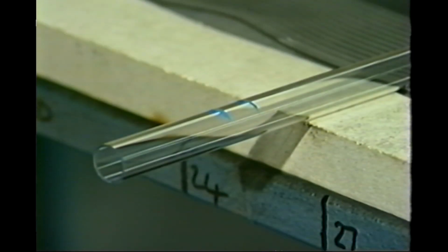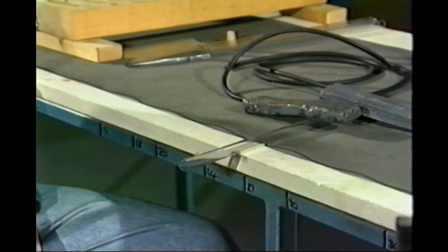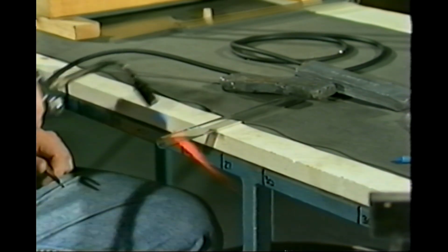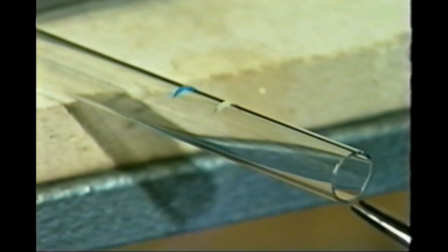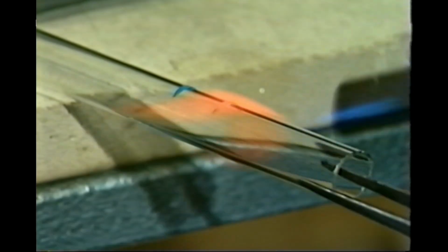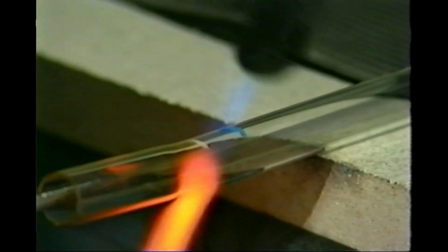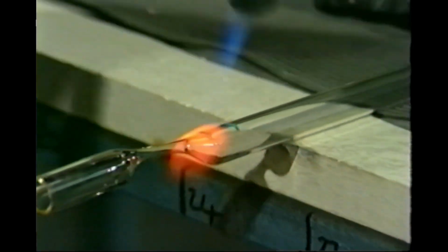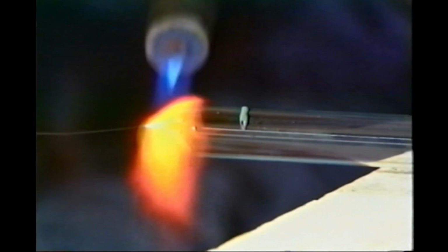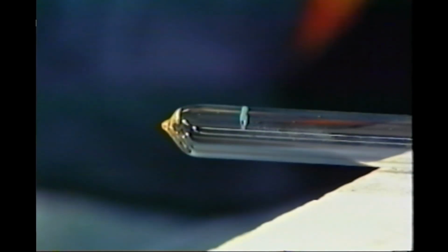Mark the position of the electrode with the chinograph pencil. Set up the same small sharp flame as used for the hand torch joints. Keeping the flame at a right angle to the tube, begin to melt slightly to the right of the first mark. As this area melts, keeping the flame rotating in the same position, pull off the excess glass with the tweezers until it separates from the main tube and leaves a closed end. The now closed end will be slightly pointed and still have some small excess of glass which must be removed.